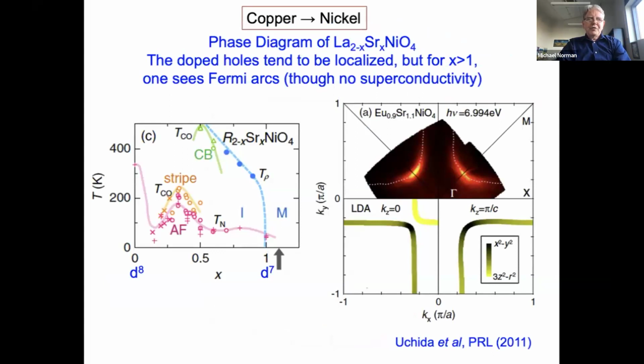In fact, I think one of the first theory stripe papers I saw on this was by Jan Zaanen, who unfortunately passed this month. If you look at the phase diagram, you see a series of stripes and checkerboard phases, and the material is basically insulating. You have to push beyond 100% doping to formal valences less than d7 before you even start to see metallic behavior, and you start to see something that looks like Fermi arcs. But to date, no evidence for superconductivity in these doped 214 nickelates.